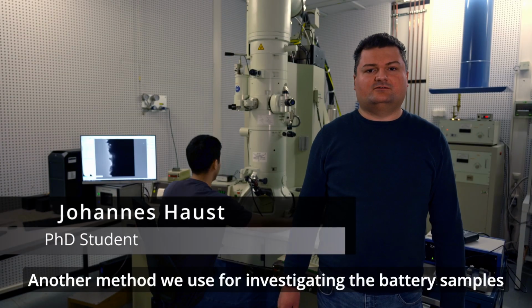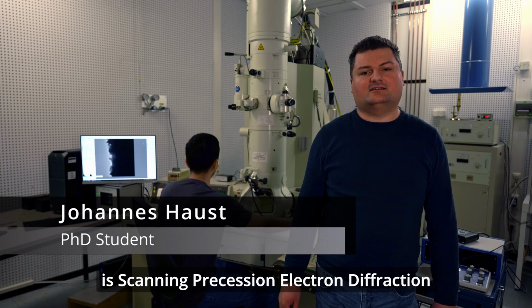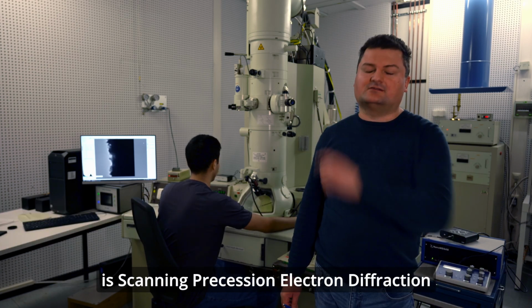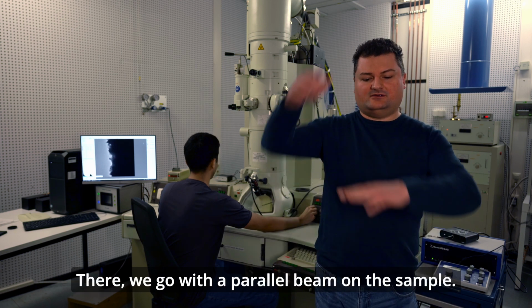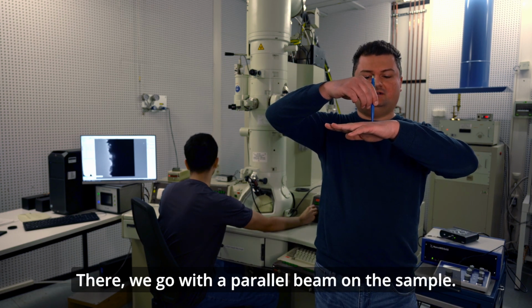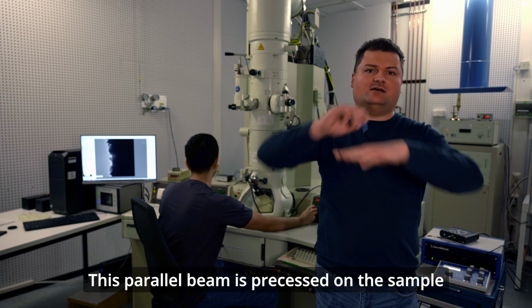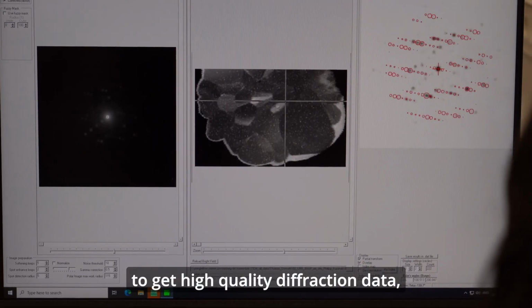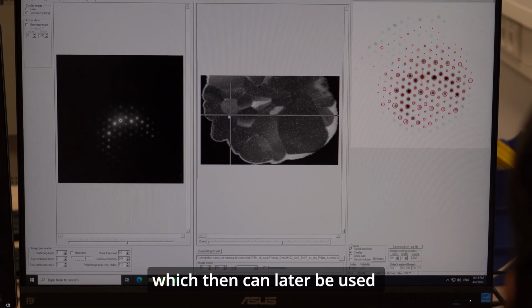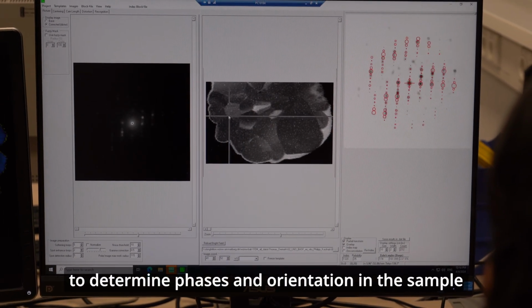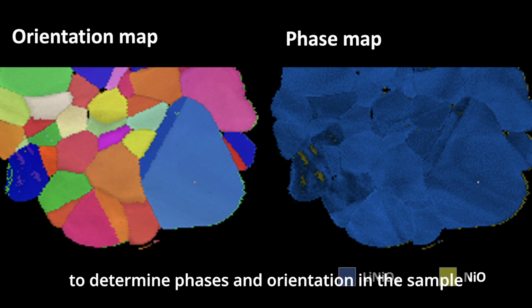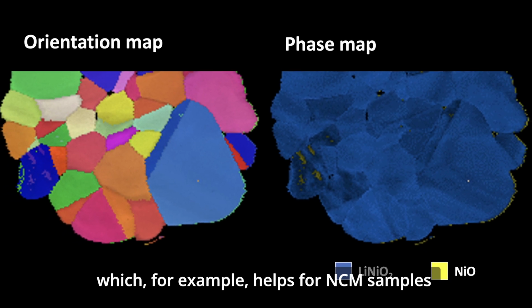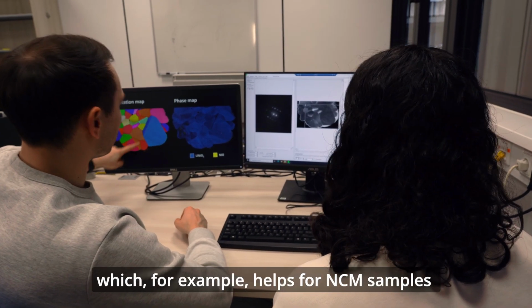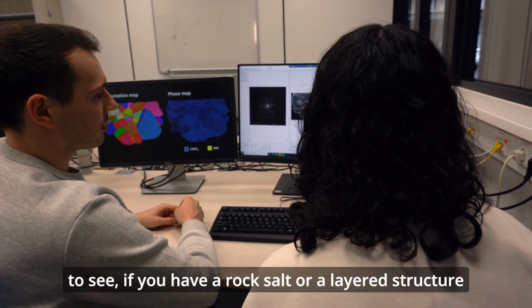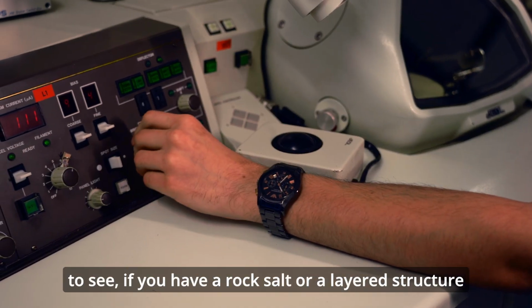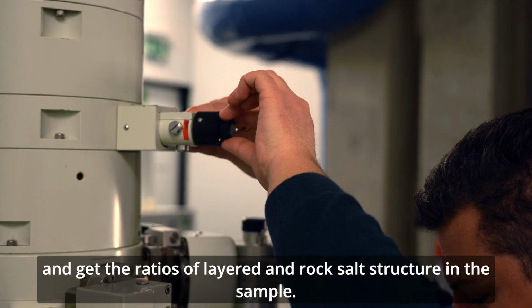Another method we use for investigating the battery samples is scanning precession electron diffraction here on this microscope in the back. There we go with a parallel beam on the sample. This parallel beam is precessed on the sample to get high quality diffraction data, which can then be used to determine phases and orientation in the sample, which for example helps for NCM samples to see if you have a rock salt or a layered structure and get the ratios of layered and rock salt structure in the sample.